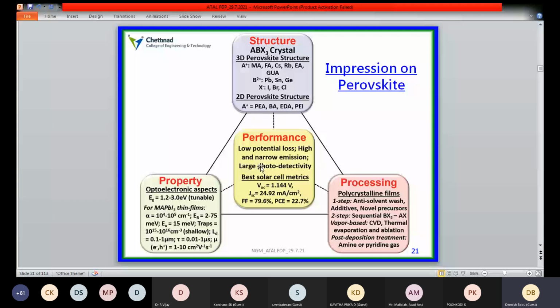And sometimes people have also looked at other two-dimensional perovskite systems, replacing the A site with two-dimensional organic cations like phenylethyl ammonium, butyl ammonium, and ethylene diammonium. In this way, they can fabricate the perovskite structures.